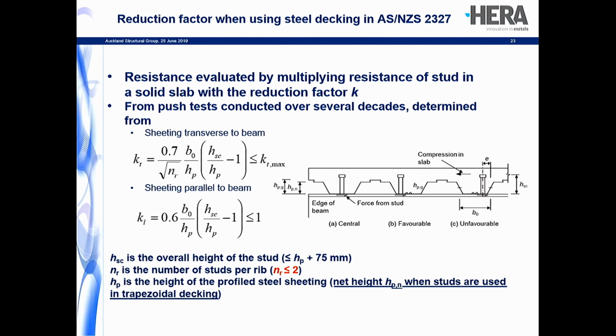When we have a shear connector welded within profiled steel sheeting, typically the resistance reduces, and it's probably quite obvious, as you can see from the right-hand side diagram, that because you've basically got a void in front of the shear connector, there will be some sort of reduction. And to allow for this reduction, what most international standards do is they have a so-called reduction factor that the engineer multiplies to the resistance of a stud in a solid slab to enable you to give a capacity which will be appropriate for a stud welded in profiled steel sheeting.